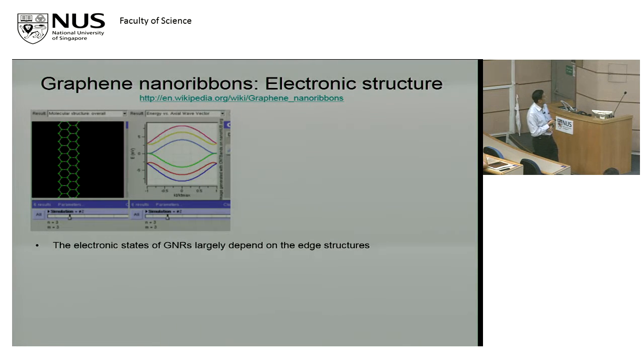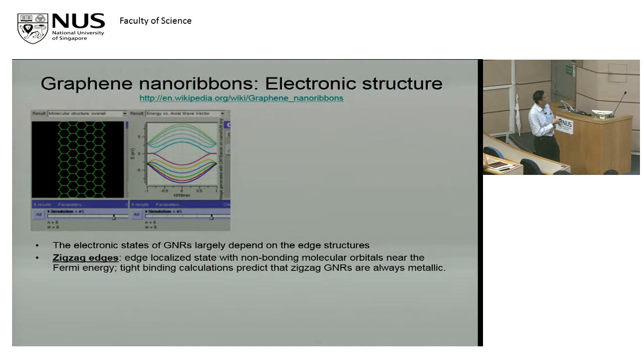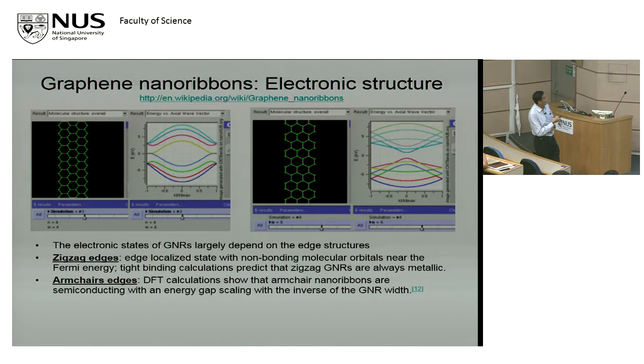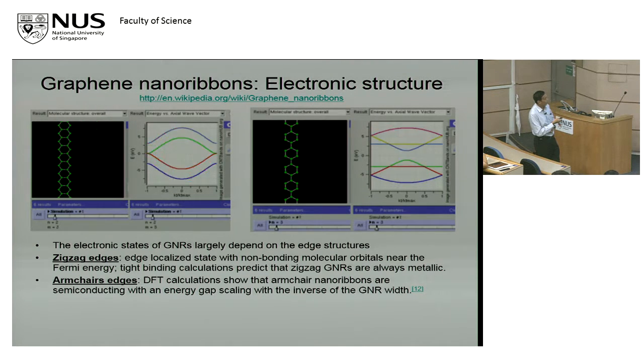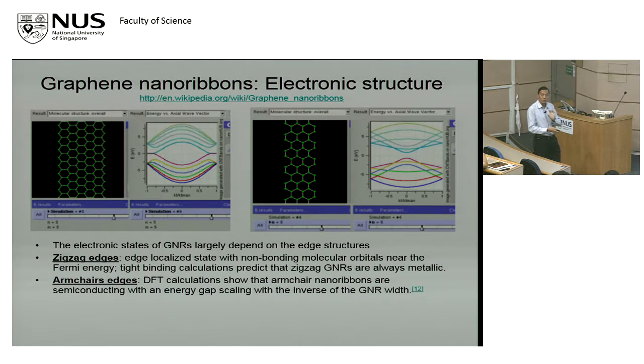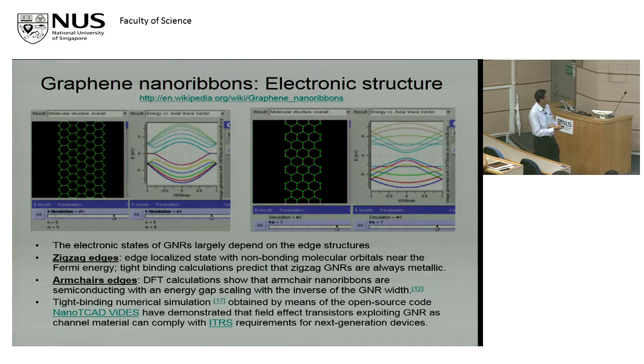So this simulation shows that actually for graphene nanoribbons, it's a bit more complicated. The electronic states depend a lot on their edge structures. So if the edge is zigzag like this, it's always metallic. There's no band gap in this simulation. But if the edge is armchair like this, you can open a band gap at certain widths. Okay? So that's the theory, or the simple theory of it.